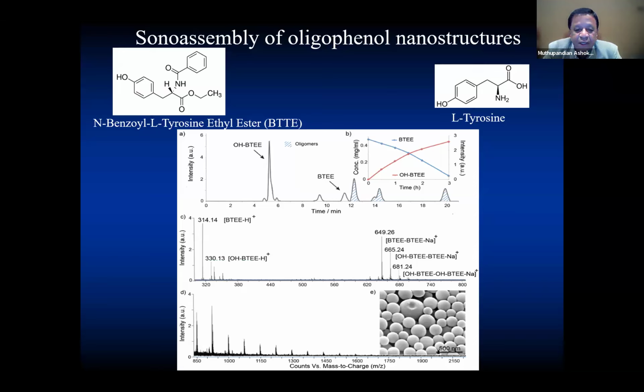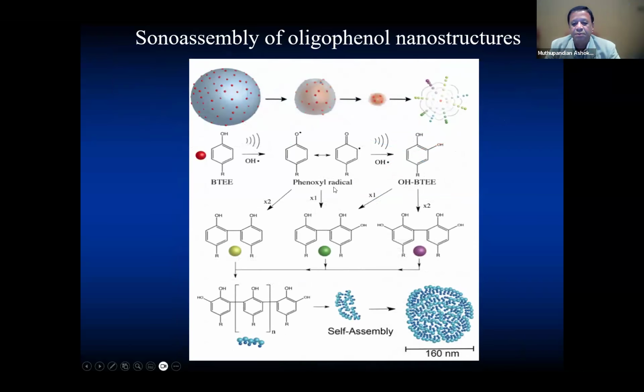biofunctional effect. So here what we have done is we have used a sonication process. For example, we took this molecule and, using sonication or the oxidation radical that we generated, converted them into nanoparticles. Again, for those who do not have chemistry knowledge, it will be difficult for you to understand this. But what I would like to highlight here is that this methodology can be used to increase not only the nutritional value, but also for drug delivery purposes. So you can use some molecules which are active against cancer, for example. Then you can use this process to convert them into small nanoparticles. And that way, the efficiency of the drug intake will be much, much higher. The process is quite complicated.